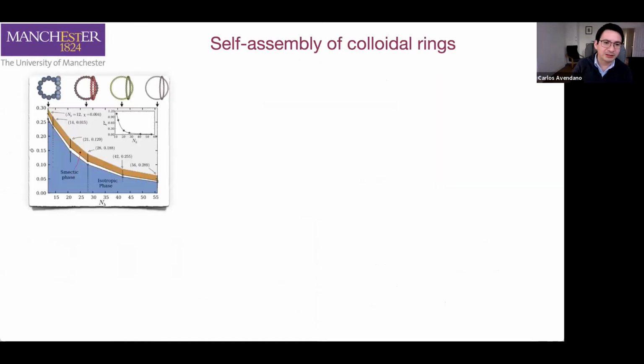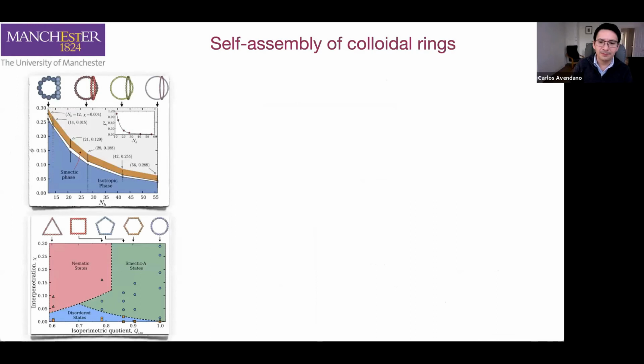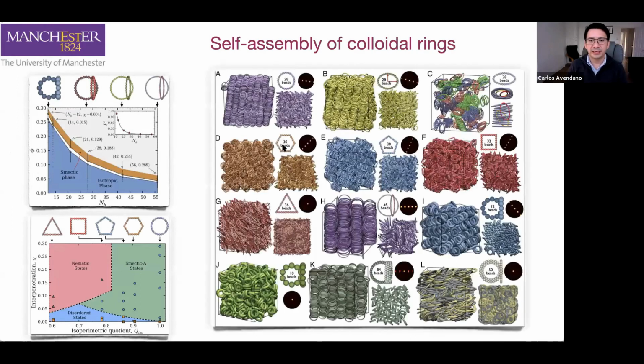We started to analyze this system even more. For example, we studied different shapes of the rings and also different aspect ratios of the rings. And what we observed was a very rich phase behavior of these systems. But the most important thing is that the densities that we observe are always extremely low. Even for this very thin ring that we have here, the packing fraction that we obtained was about 5%. So basically it's almost empty space in this system.